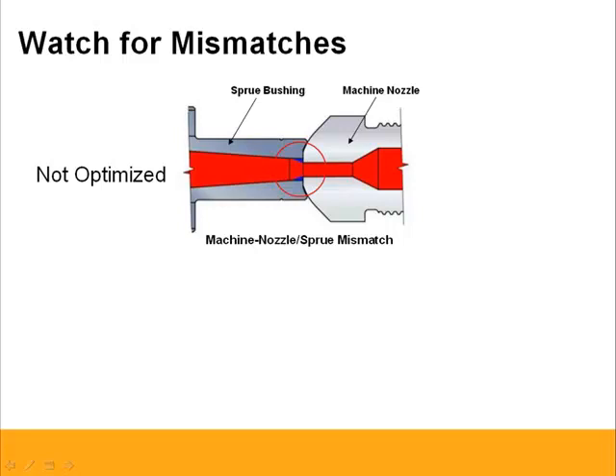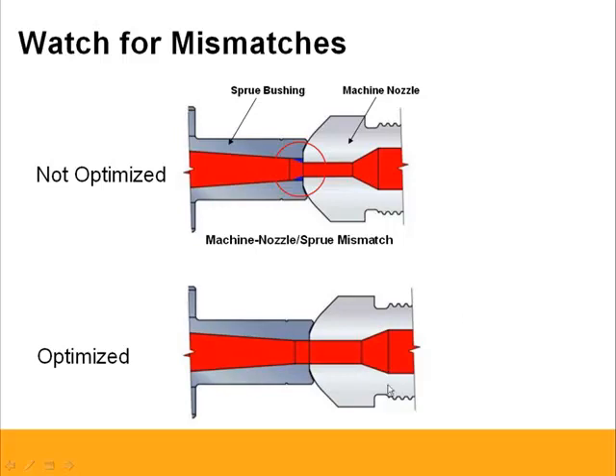But a mismatch of 1 or 2 millimeters won't actually hurt your injection molding capabilities, but from a color change point of view, what you just created is basically a dead spot of the old material sitting there, not moving, and then continuing to bleed into the melt stream and prolonging your color change. So always a good thing to check. An optimized version, of course, is to make sure that the machine nozzle orifice and the sprue bushing orifice match with each other. A similar problem could be worn out surfaces and dead spots in this area, that will cause problems too.